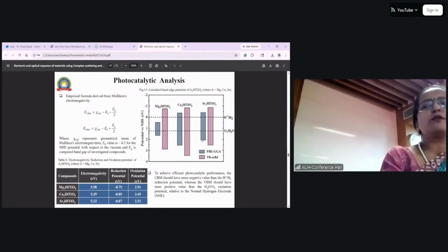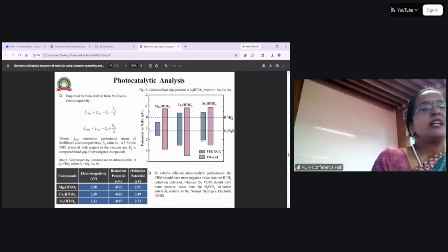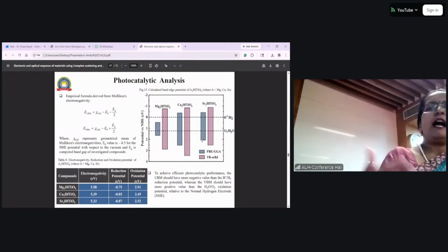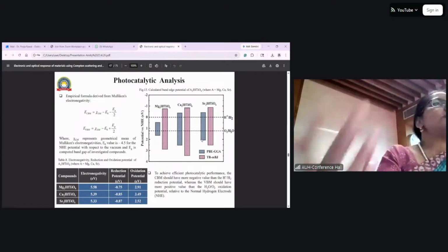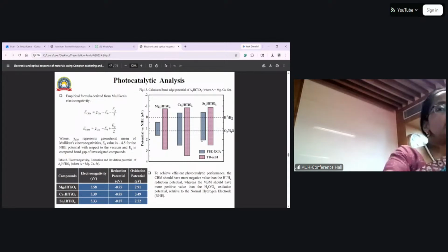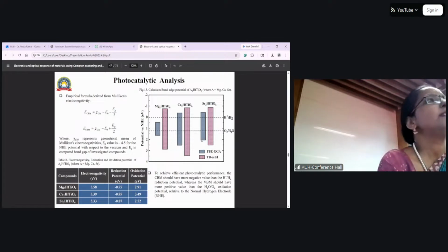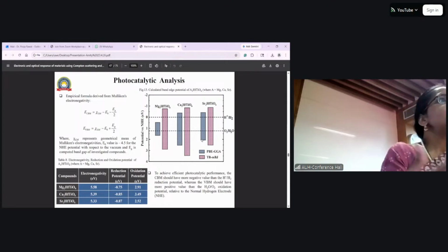So for the photocatalytic activity, the valence band edge and the conduction band edge should be in such a way that the valence band edge should be below the oxidation potential of O2, and the conduction band should be above the reduction potential of hydrogen. In our case, this was observed for all the compounds. The reduction and oxidation potentials all had values above the acceptable value. So in this particular paper, we found that our materials are suitable for photocatalytic application also.